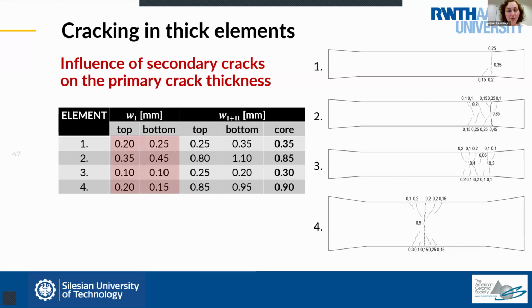But if we add together the width of all the cracks that form a kind of a set of cracks, so a primary crack and the secondary cracks, we can see that the total width of this system of cracks equals the width of the crack in the core. So what does it mean practically? It means that when we have a real structure, we usually check the width of the crack on the surface, because this is the only thing that we can actually do.